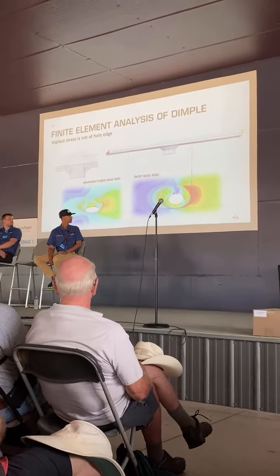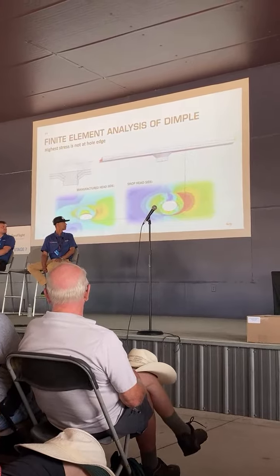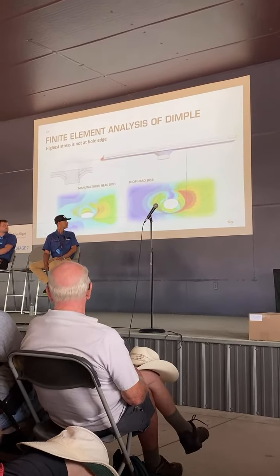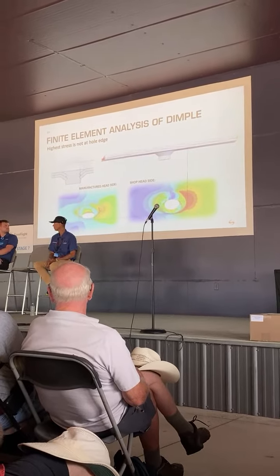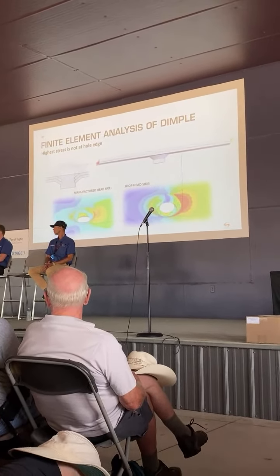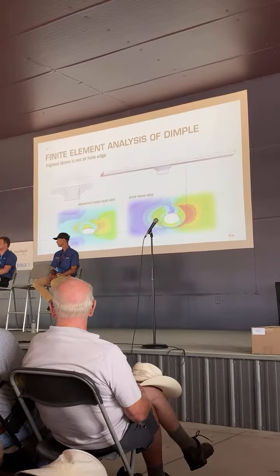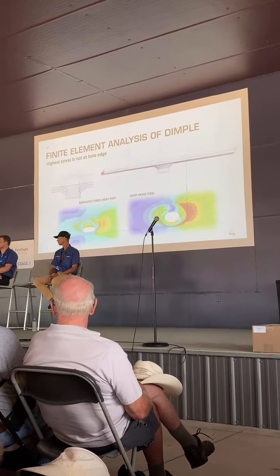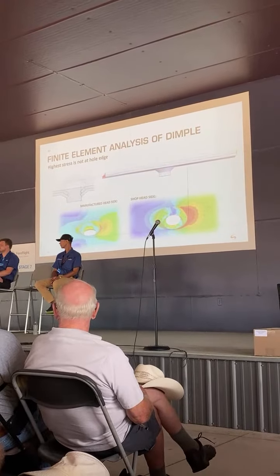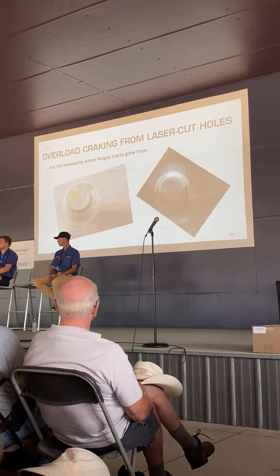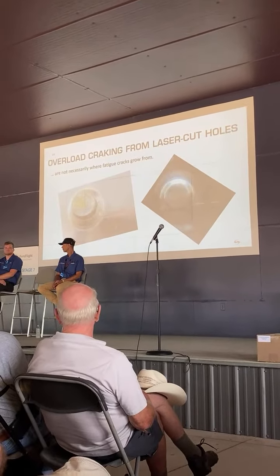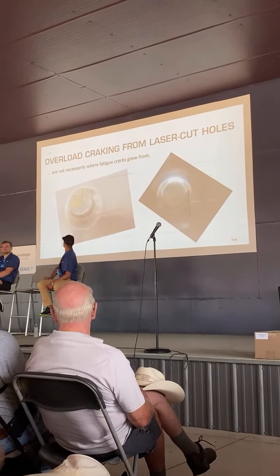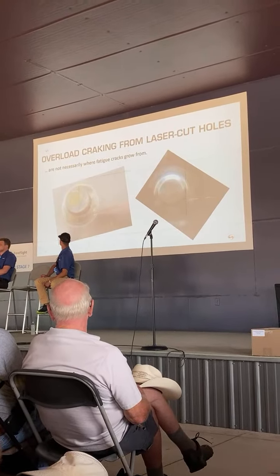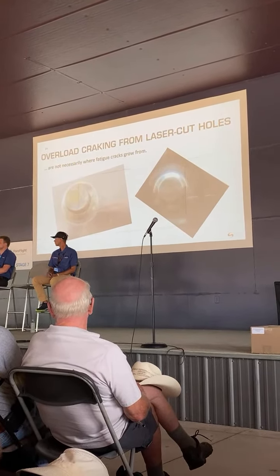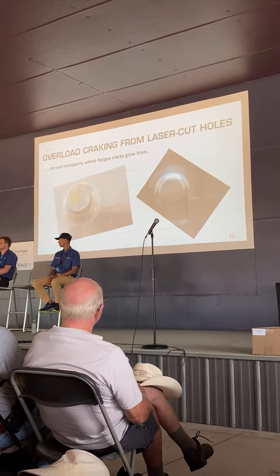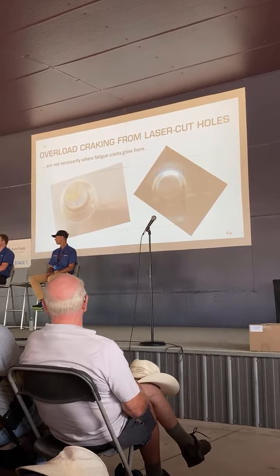So we're taking the features we've tested here at the 3 and the 9 position, and we're currently gathering test data at 45 degrees and here at the 12 o'clock, 6 o'clock positions as well. So far, that testing is showing equivalent life to the other test, the 3 and the 9 position, which is the graphs we saw earlier. Here's pictures of actual cracks. You can see here is the overload feature, and here is the crack itself that's going to the edge of the hole. And we're constantly asking ourselves, why is this the case?